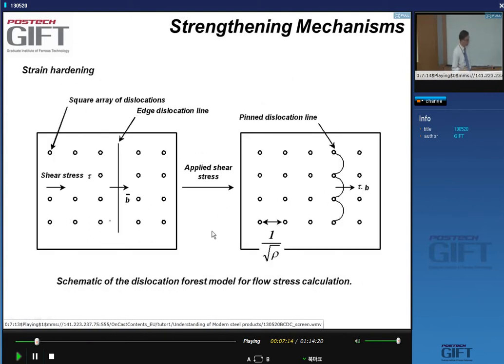All right. We also know that the strengthening due to these forest dislocations is proportional to the density of dislocations. And if we assume that the dislocations form a regular square pattern, then they will be spaced a distance 1 over the square root of the dislocation density.